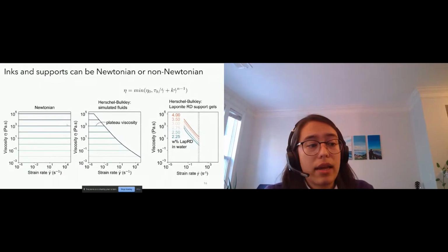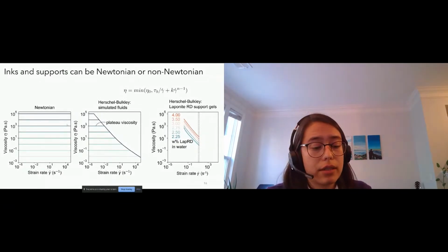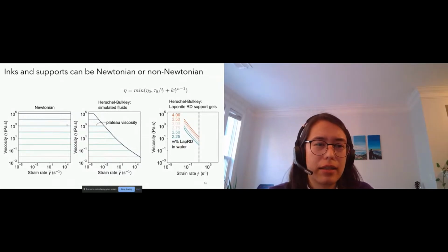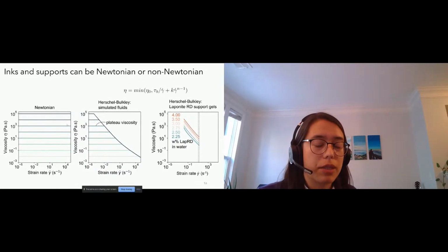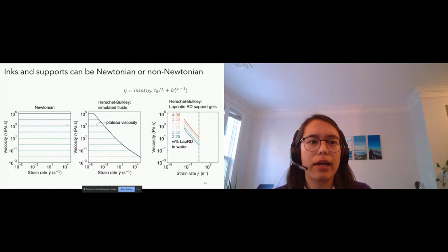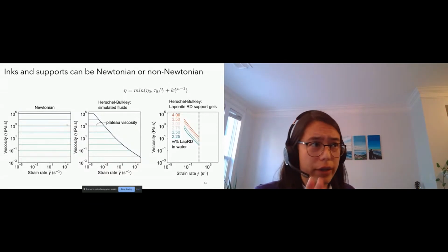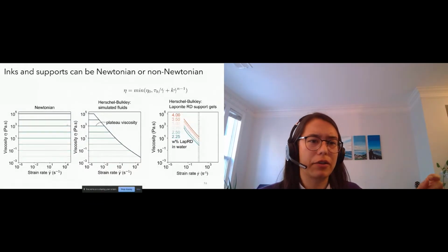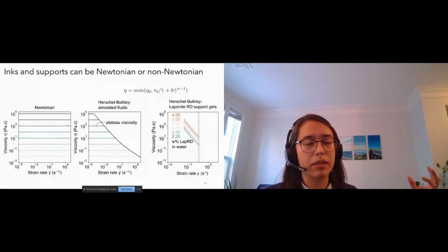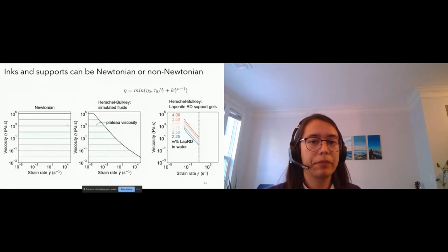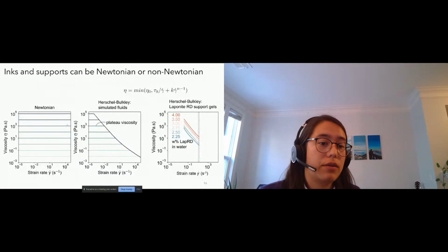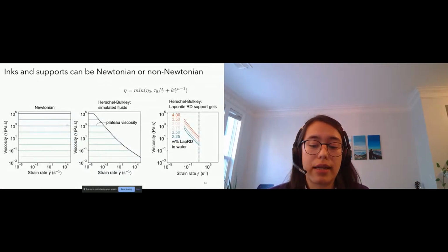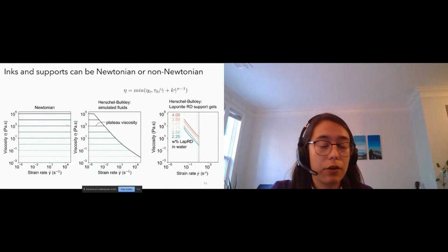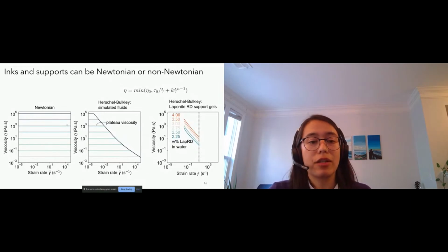So one type of material that has been printed is the Newtonian material. Usually in these papers where they're using Newtonian materials, they'll have some sort of stabilizer at the interface. So they'll be printing oil into water, but they'll have a particle that stabilizes the interface so that the material doesn't break up into droplets. In our simulation, we use Newtonian fluids in order to identify what is the effect of viscous dissipation on this process. We don't want to have to worry about yielding or elasticity or anything else, just viscous dissipation.